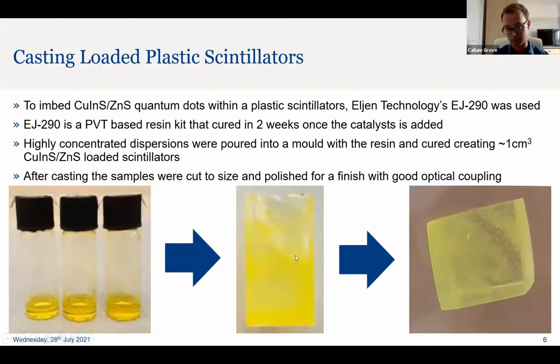So you can see that there's a significant concavity at the top, which is where you had shrinkage when polymerization occurred, which just needed to be cut off the top, which is why we were trying for cubes, but we allowed for extra height. So we cut the top off and then polished them and produced this as an example of the homogeneous batch.